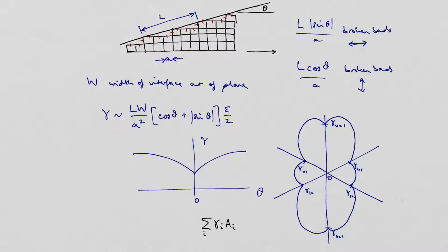That's the point of this basically, that the surface will tend to be at the... Right, so I haven't quite got there yet. What the system wants to do to minimise its energy is to minimise this. It wants to choose a set of surfaces I such that the sum of the product of the surface energy per unit area times the area is the smallest that it can possibly be.